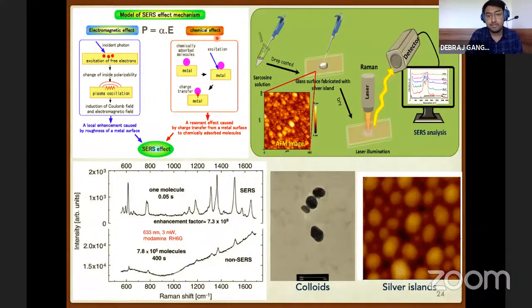Another process is the chemical effect. In the chemical effect, there can be direct attachment of the ANALYTE with the metal surface, and by charge transfer, this polarizability value may increase, and this may cause a huge enhancement in the Raman signal. Most commonly, there are two kinds of SERS substrates that we use: the colloidal nanoparticles of gold or silver, and the silver island film, or thin films, where we deposit a thin layer of silver or gold on a glass substrate.